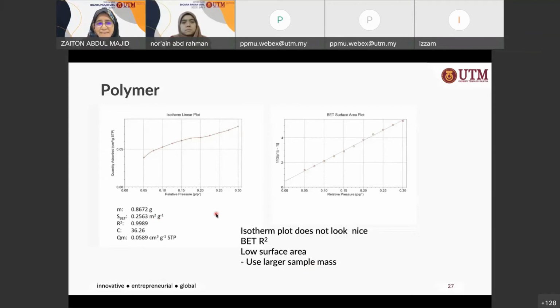So in this case, they suggested that for low sample BET surface area, you need to use larger sample mass. You have to make sure that your R square is 0.9999. Okay. Another example.